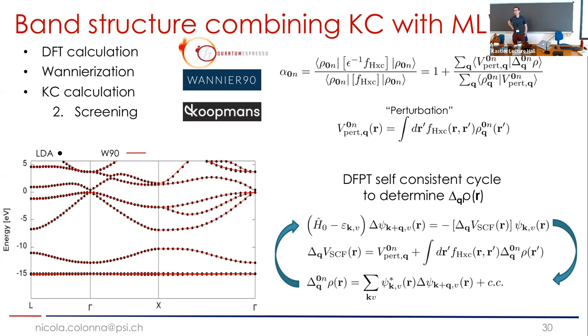Maybe a quick comment on this, in the sense that the KI functional has exactly the same total energy as the base functional you start with. So it's not giving you improved energetics from LDA or PBE or PBEsol. The KIPZ functional adds this Perdew-Zunger self-interaction correction with a screening coefficient that comes, if you want, from imposing a spectral property, imposing a linearization. This seems to be working well. So it's basically a local screened Fock term.